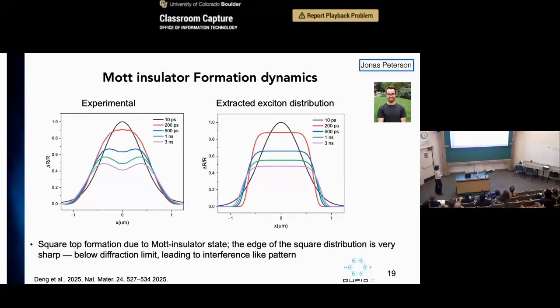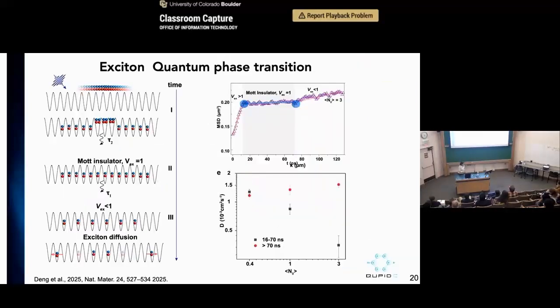And if you extract the one-dimensional spatial profile from those images, what you can see is that initially you have a Gaussian, because that's what your pump is. But then as time progresses, it becomes a square wave, and you have these edges as well. The reason you have these two lumps on the side has to do with the limited spatial resolution of our imaging system, actually. Because the edge of this Mott state that we created is quite sharp, it's below our diffraction limit, so it is convolved with the spatial beam profile. You can deconvolve it, and you can see that you go from a Gaussian-like distribution to a pancake-like distribution, which, again, is what you expect from a Mott state.